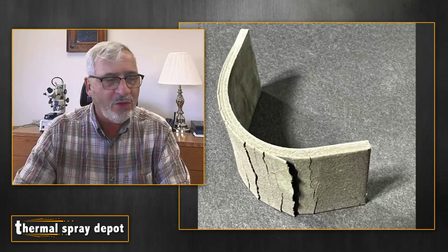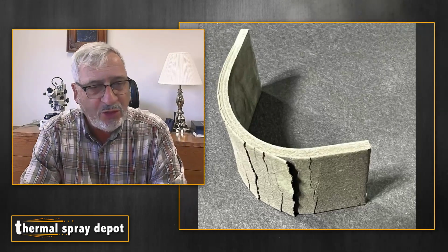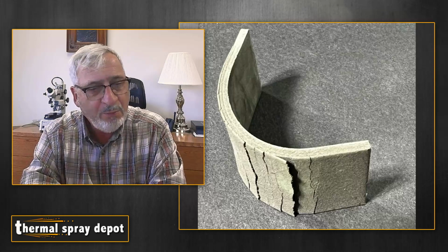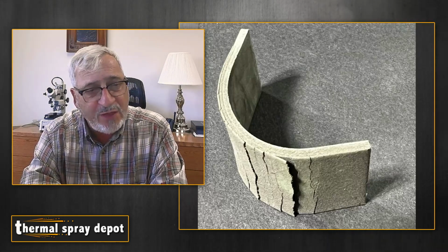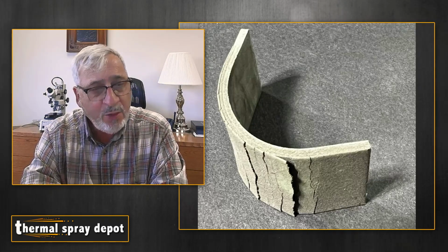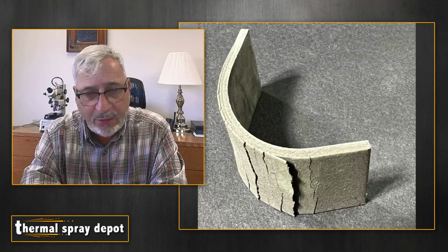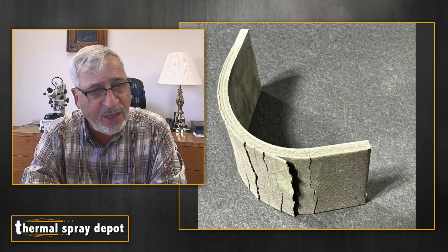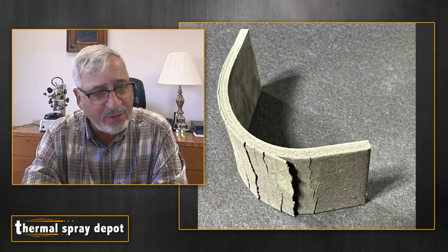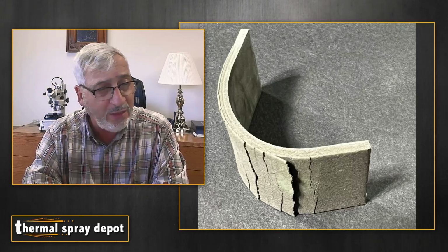But for the point of discussion here, it's exactly what I would have anticipated looking at a zinc coated or thermal sprayed coating done with zinc on a girder. Now, this is what's called a bend sample, and this shows how a spalled coating pops off. In this case, this part was sprayed when this test strip was straight. Then we put it in a vise and started bending it around a radius. Now, this was a pretty big radius.